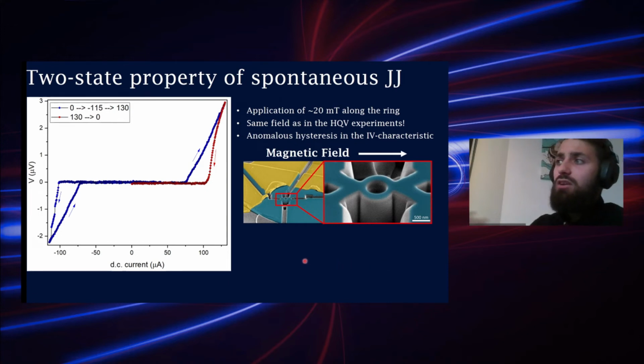Then what we find is an anomalous hysteresis in the IV characteristic. Let me walk you through it. We start at zero current and increase the bias towards the negative side. We see a critical current where we go to the resistive state, and a retrapping current that is smaller than the critical current. This is fine, this can happen in overdamped junctions. However, when we go to the other current polarity, we see that the critical current is smaller than the retrapping current, which is highly anomalous.